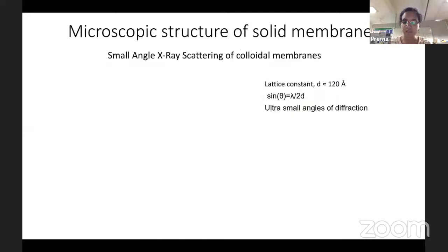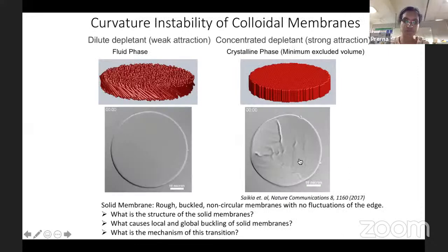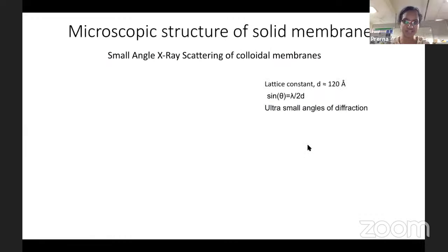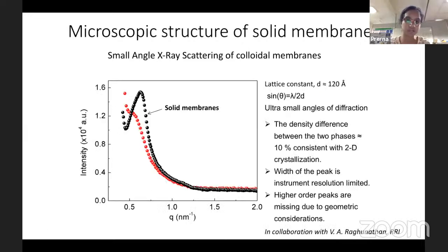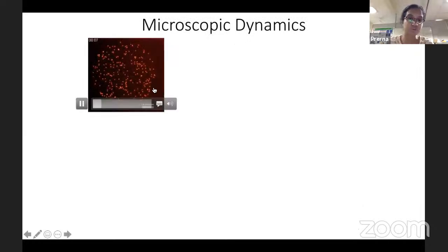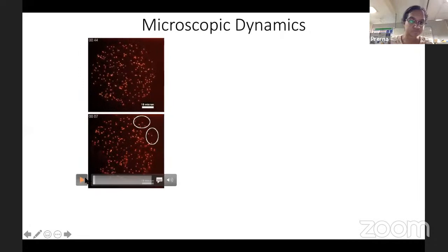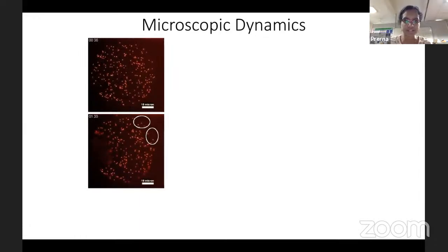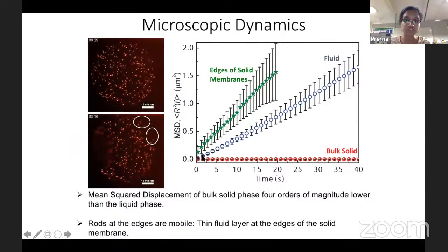So essentially, first I need to really prove that this is crystalline. If I want to prove that the sheet is crystalline, I need to do some kind of diffraction experiment. Because the length scales are very large, the diffraction angles become very small, and so we use what is called small angle X-ray scattering. We found a well-defined peak for our solid membranes, which showed us that indeed these are crystalline. You can also look at the dynamics. Here you have a fluid sheet where all the rods, the individual dots, are moving around. If you look at the solid sheet, you will find that all the dots are static. The rods are completely frozen in, and you can characterize it quantitatively by measuring mean square displacement versus time. For the fluid, it will look like a linear graph, whereas for the solid phase, it's a very small number and flat as a function of time.